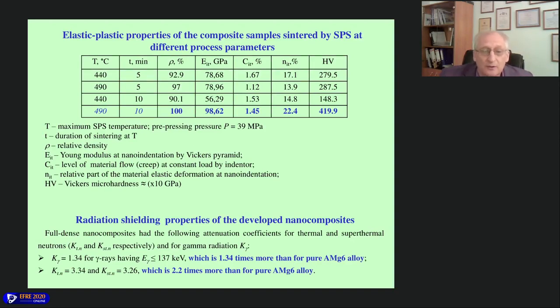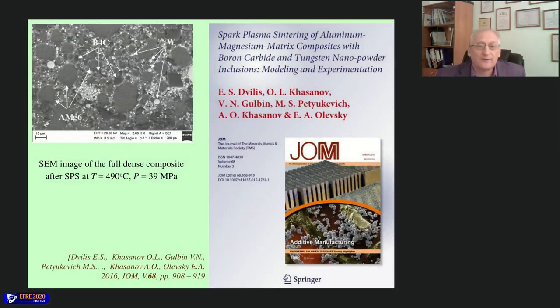Attenuation coefficient for gamma rays was 1.34 times more than for pure aluminum magnesium alloy, and for thermal and super thermal neutrons, this attenuation coefficient was 2.2 times more than for pure aluminum magnesium alloy. These results were published in several